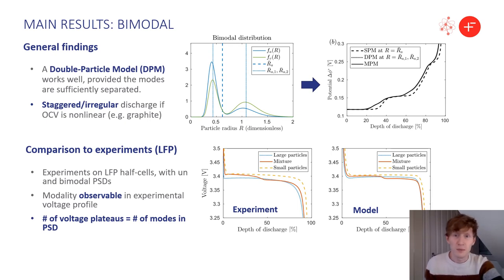We also made some specific comparisons to experiments on lithium iron phosphate, clearly demonstrating the effect of bimodal PSDs. Bimodal PSDs can be made by mixing a source of small particles and a source of large particles. Only the mixture exhibits a step in the discharge curve between two plateaus, and this is captured by the model.